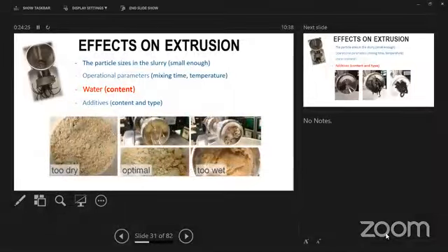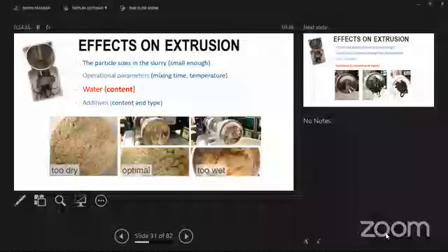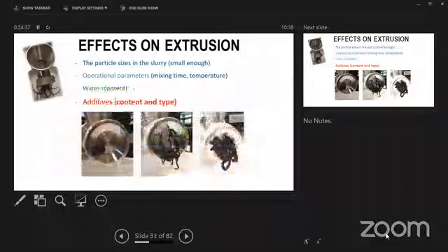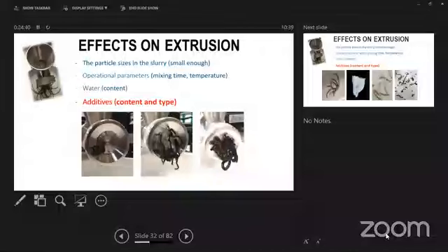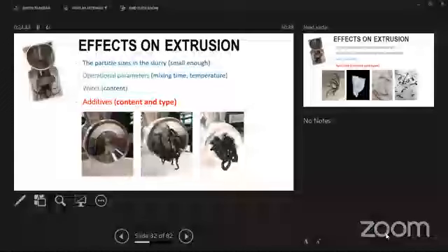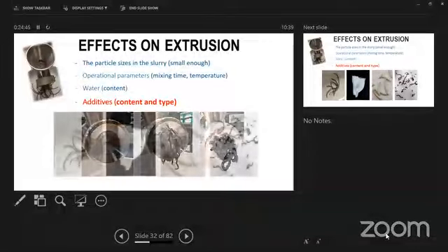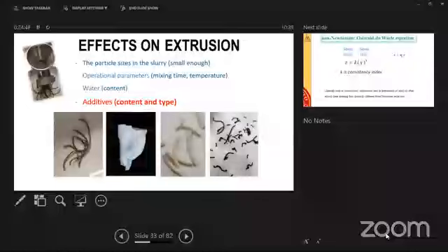So if it's too wet, then we might have something like that. That was the optimal content, and maybe if it's too dry, then I will not even be able to make paste. Some other examples when we have different additives and we see that we can fail. And we actually failed many times.